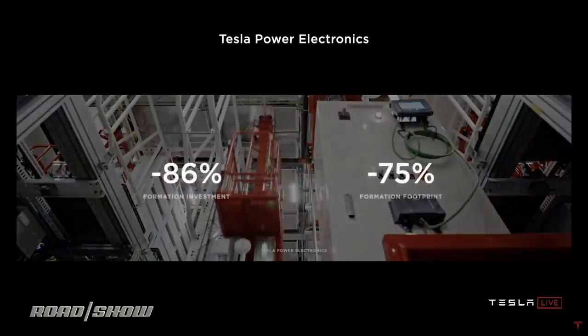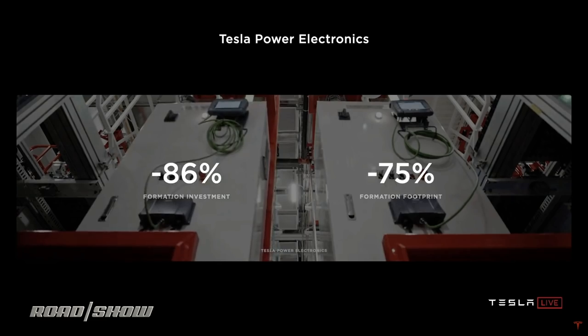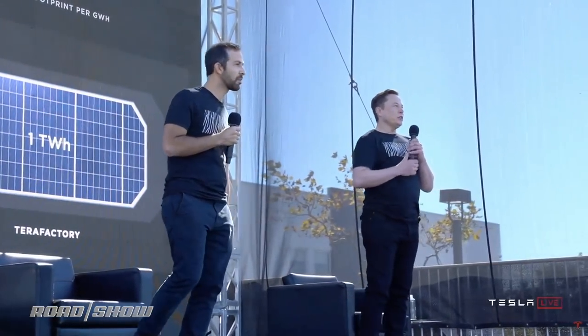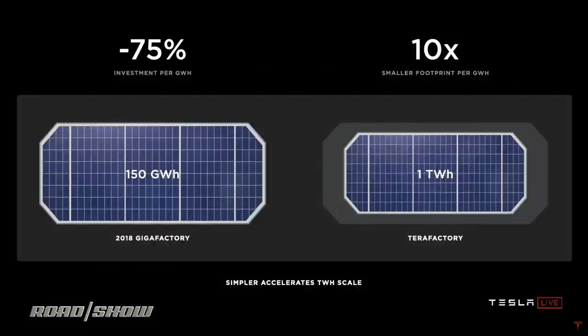86% reduction in formation investment, 75% reduction in footprint. So essentially what this translates to, based on what we know today, is about a 75% reduction in the investment per kilowatt hour or gigawatt hour. It's just we're able to, from a volume standpoint, actually get, in a smaller form factor than Giga Nevada, many times the cell output. So you can see, basically we can get a terawatt hour in less space than it took to make a gigawatt hour, 150 gigawatt hours.